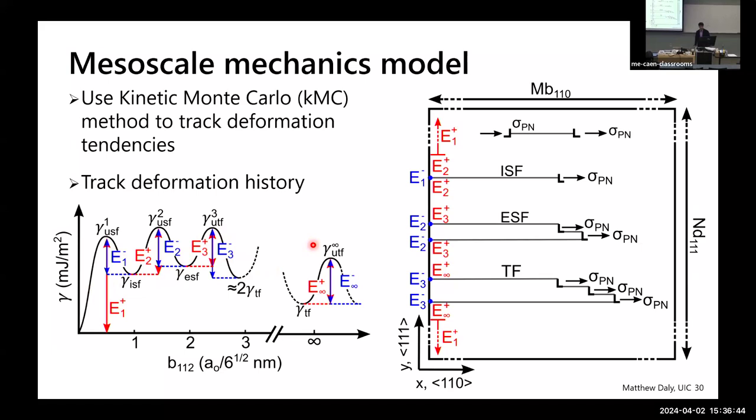So again, just to reiterate what we're doing: KMC model, treating every location on this model as a nucleation point on the left-hand side and glide points through the model, populating this model with barriers. These barriers are drawn from the generalized planar fault energy. So it's a completely intrinsic mapping to deformation mechanisms between slip and twinning. And then we're throwing our dice and seeing what comes out.